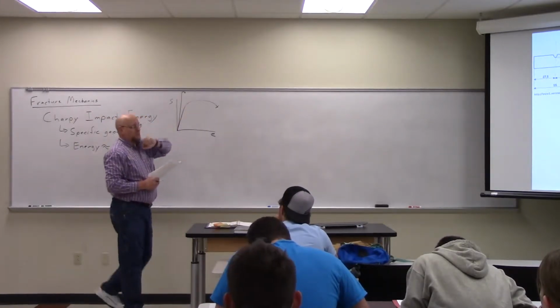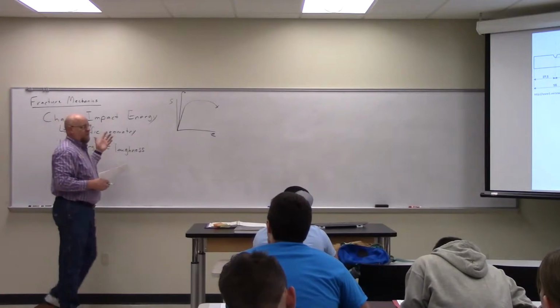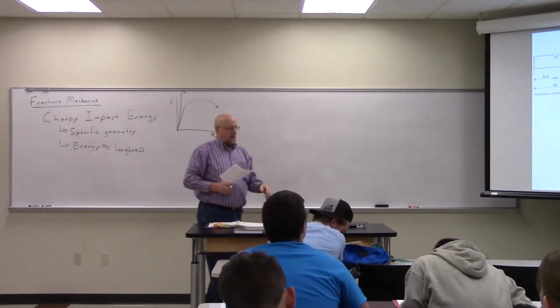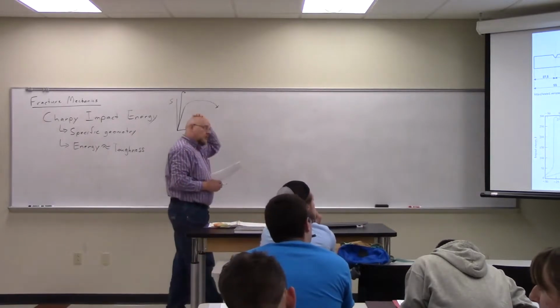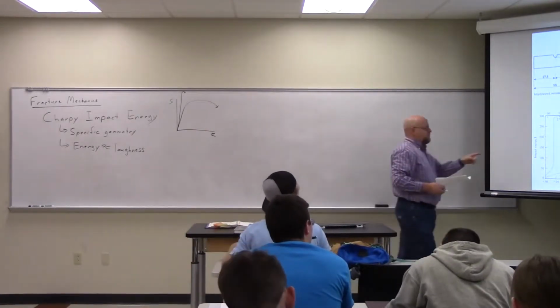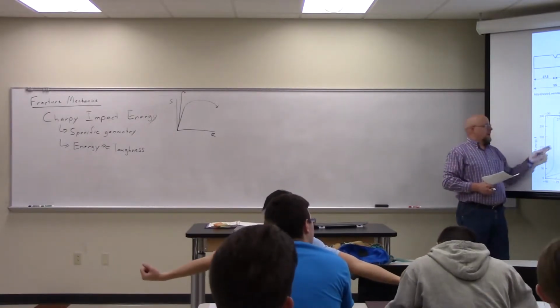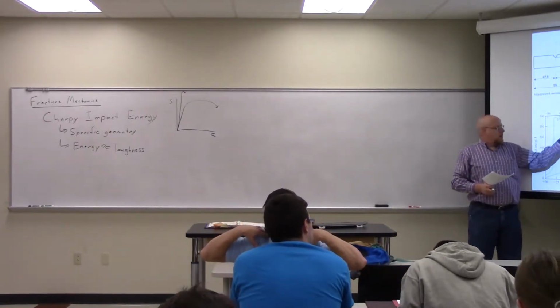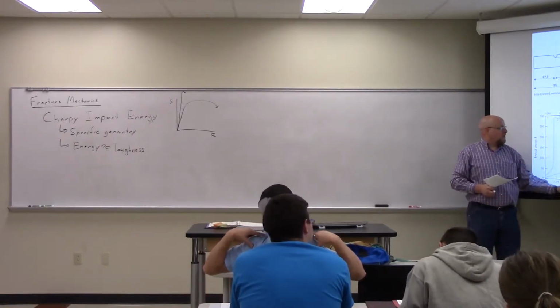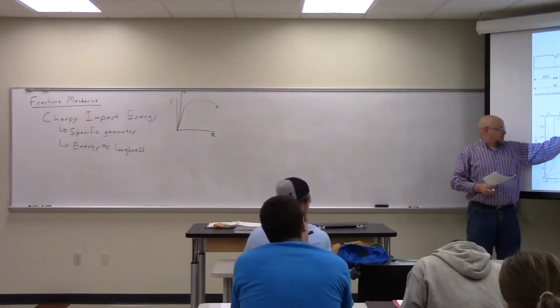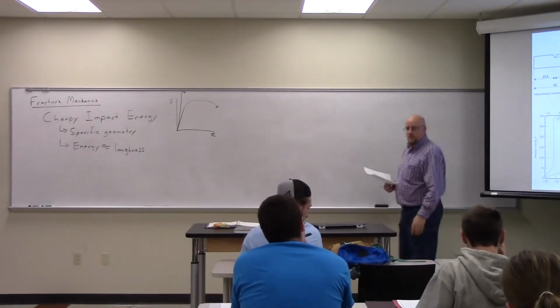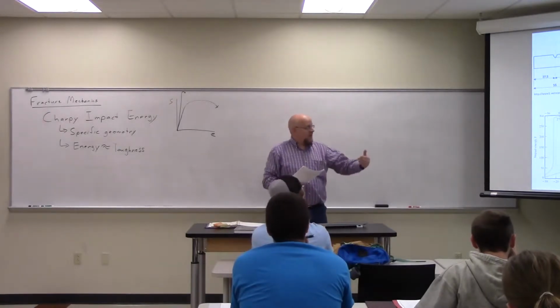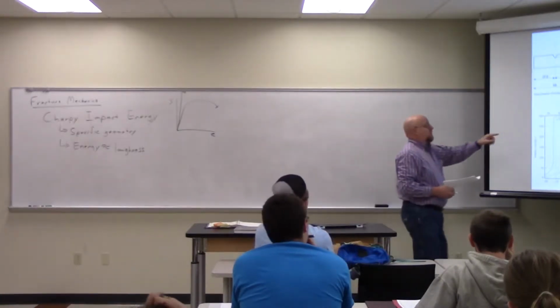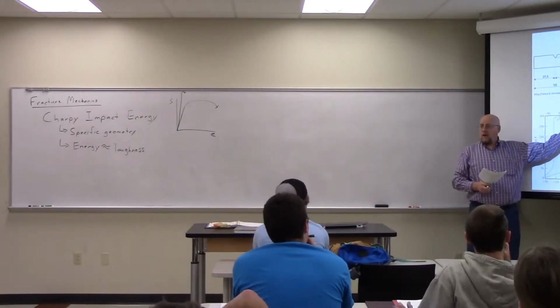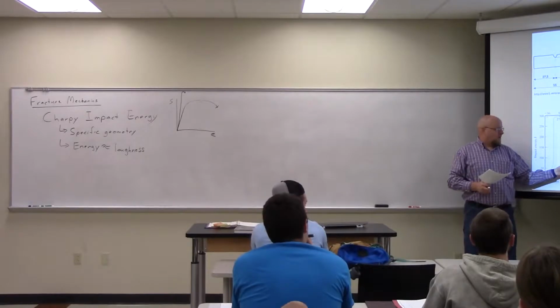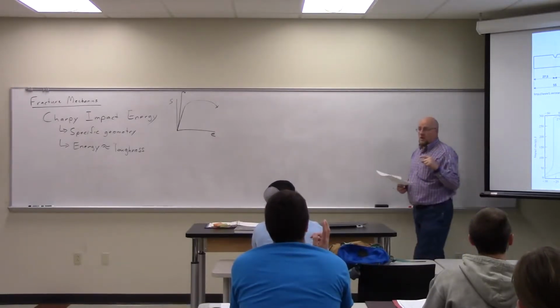And so we can map the Charpy impact energy as a function of temperature in this case. And we can see that what happens is materials, just take one of these as an example, has a very high Charpy impact energy at a high temperature. But there's this well-defined temperature, 25 degrees C for this particular material, where the impact energy dramatically drops off. What that means is, above 25 degrees C, that material is very ductile, has a very large impact energy, has a high toughness. But below 25 degrees C, it has a very small impact energy and behaves brittly.